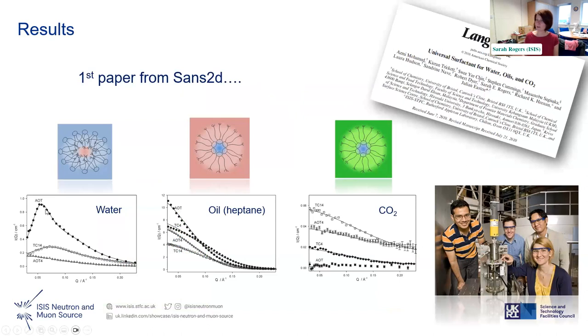And the first paper to come from Sans2d was actually on some of these systems, where we had designed a special tri-chain surfactant. It had three tails. And this was not only working in CO2, as shown here, it also worked in water and in oil. So we basically designed a super designer surfactant that works in any of the conditions that we're interested in. And the image there is of me a long time ago, because it's the first Sans2d experiment. And that's the special pressure cell that we use.